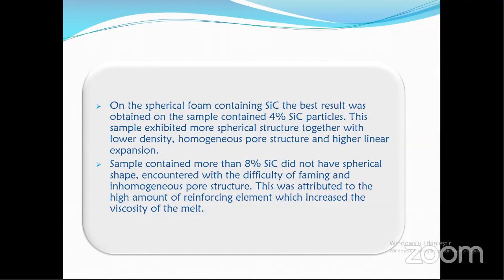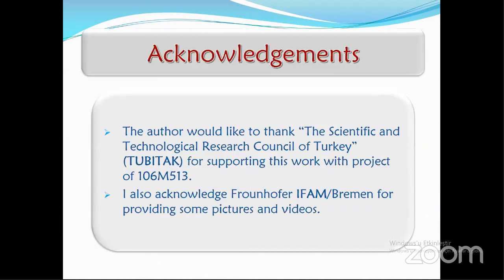Samples containing more than 8% silicon carbide did not have a spherical shape and encountered difficulty in foaming and an inhomogeneous pore structure. This was attributed to the high amount of reinforcing element, which increased the viscosity of the melt.